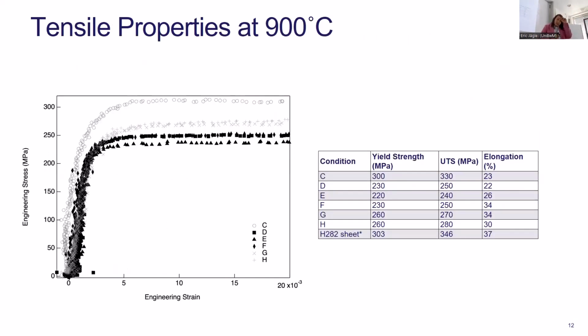So tensile properties at 900 degrees Celsius, apart from the one that we quickly cooled, which gave us a much finer gamma prime distribution, everything else is within error. So everything is equivalent. The elongation, you can ignore. The electrothermomechanical testing is very bad for elongation. The main thing I included it for is just to say it's not brittle. So it has quite a fair amount of ductility after all of these heat treatments. So there isn't a massive debit on the ductility even at temperature.